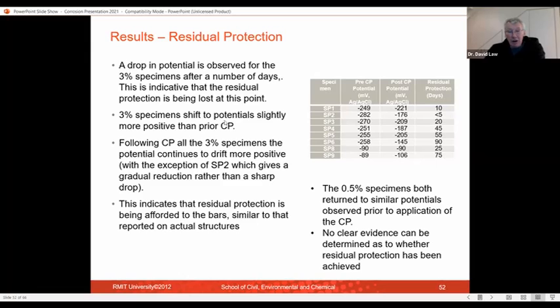Overall, there was no clear evidence as to what was causing that loss, but we were seeing residual protection in all of the bars for a period of time similar to what we'd actually seen on the actual structures and had been reported. When it came to the length of time and the amount of current passed, we saw no clear relationships based on these short-term trials, however, to be able to say that it was the time or the total current that was affording us better protection.